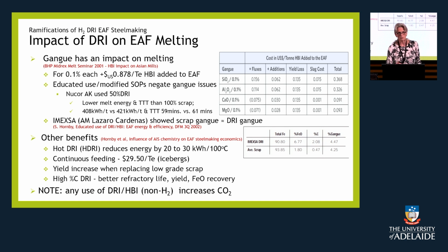Gangue has a big impact on what happens in the arc furnace, and this is a chart from a paper that David Trotter and I et al. wrote way back when, and it actually quantifies a dollar value for every 0.1% of the gangue that's in an iron. If you add it all together, although you wouldn't have that in a situation, you're looking at close to $1 per percent, $1 per ton if you've got 0.1% of each of these being added to the furnace.